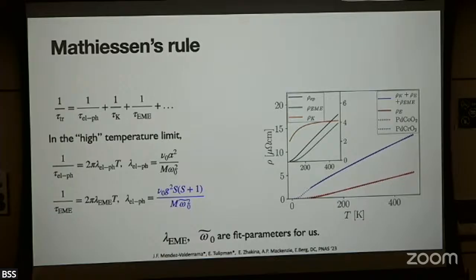The out-of-plane phonons? First of all, this is something I'm making up. I don't know directly from experiments. You can assume either one. For the high temperature, it doesn't matter. I mean, the onset temperature matters, but of course the low temperature regime matters. So it turns out in this particular example, if you assume acoustic phonons, the low temperature regime can give you a T squared, if you think of this as 2D, and not T to the fourth, because of some interesting mechanism for momentum relaxation. But for the high temperature regime, it could be either. In reality, which one it is, I don't know.